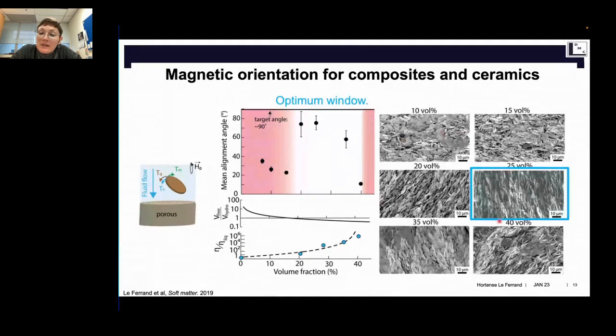And you can see this now in the SEM images. If it's too dilute, it's kind of random. If it's too concentrated, it's also kind of random. But there is a sweet spot around 20-25 volume percent where we can really align the platelets nicely, and then you can dry it and it will stay aligned in the very nice direction. This concentration depends of course on the platelets that are used. These are aluminum oxide platelets of a certain size. If you change the size, change the platelets, the window will change.